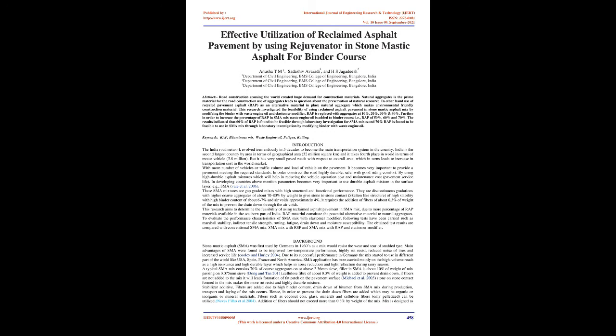Further, in order to increase the percentage of RAP in SMA mix, waste engine oil is added to the binder course, i.e., RAP of 50%, 60%, and 70%. The results indicated that 60% RAP is found to be feasible through laboratory investigation for SMA mixes, and 70% RAP is found to be feasible in SMA mix through laboratory investigation by modifying the binder with waste engine oil. Keywords: RAP, bituminous mix, waste engine oil, fatigue, rutting.